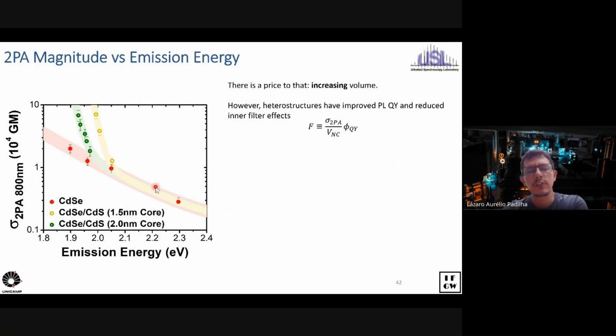Also, when you change the cross-section, we change the absorption cross-section by changing the volume. And this can be a high price to pay if you are thinking about applications, because some applications are interested in the total two-photon absorption coefficient, which is proportional to this two-photon absorption cross-section divided by the nanocrystal volume. And of course, when you increase the cross-section here, you're paying the price of increasing the volume.